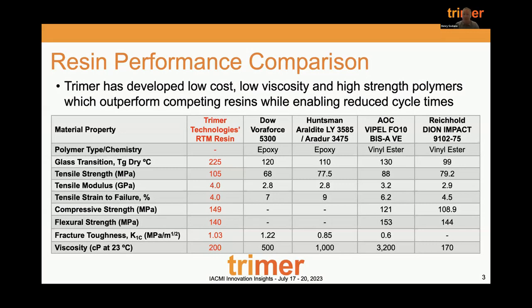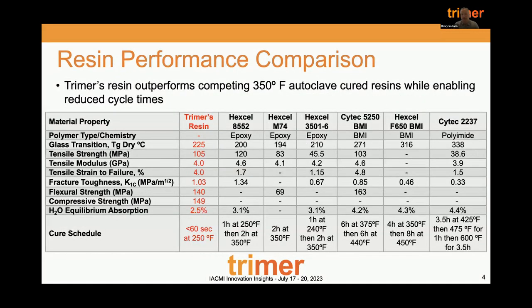These are industrial and automotive materials. And if I jump forward, this is comparing it against other resin systems that are in the aerospace industry. So the primary resin you would typically compare aerospace materials to is this Hexcel 8552. It's a polyether sulfone toughened epoxy. It has about 20 to 25% polyether sulfone, so highly thermoplastic character, but a very tough system, and we can compete with that material very well.